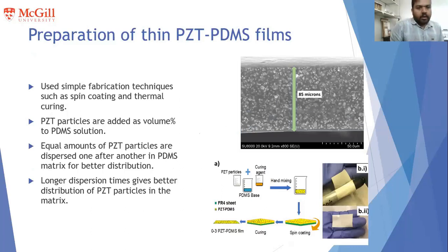Coming to the fabrication, it starts with preparing a solution with PZT nanoparticles, PDMS and cross-linking agent. Then we disperse the particles in the solution well by mixing, and we spin coat the solution on an FR4 substrate. The FR4 substrate is chosen because after curing of the solution, you can isolate the film very easily with the use of the FR4 board.